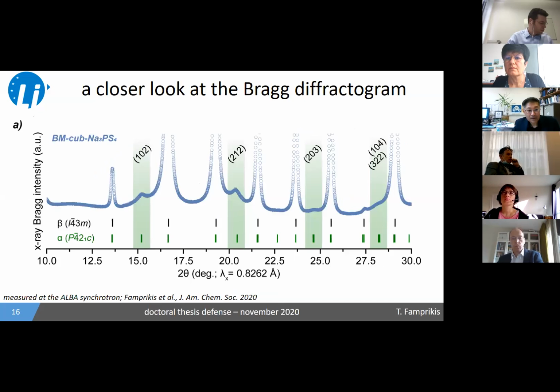So we say it's cubic, but let's have a closer look at the diffractogram I showed you just before. The main peaks are indeed indexed in the cubic polymorph, but if we look at the fit of these intense diffraction peaks, we can see very broad reflections that are actually unindexed by the cubic polymorph, and which are actually indexed by the tetragonal polymorph. So this gives us some clue as to, it's not very clear whether this comes from a secondary phase of tetragonal symmetry, or if this is somehow a superstructure attributable to the main phase, but we have some sort of clue.